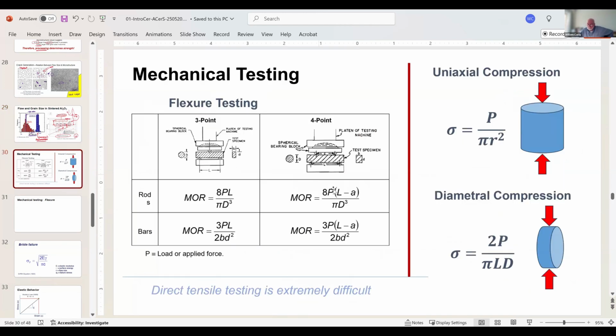Okay. So we do mechanical testing on ceramics, and I'm going to start up here in the corner. Uniaxial compression, okay? This is also called a compression test, and this is favored by DOT, Department of Transportation. It's done for concretes. And I'm convinced that it's done for a couple of reasons. One is it's a simple geometry. The other thing is the strengths are high, very high. And the reason that they're high is because of the geometry of the sample.